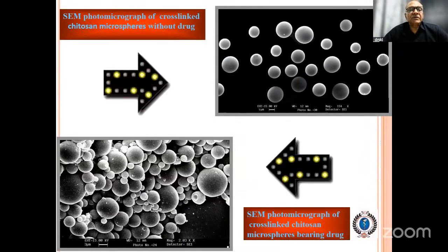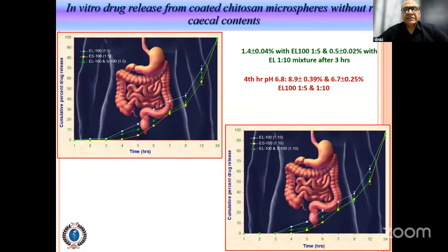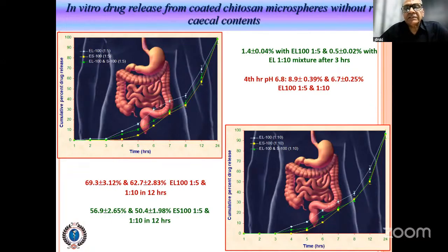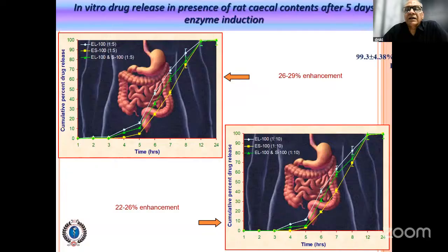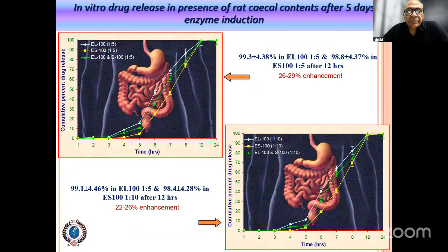This is a photograph of the cross-linked chitosan microspheres without drug, and this is the photograph of the chitosan microspheres bearing the drug. Different studies were performed to ascertain how much drug is released in the colon in the presence of the cecal content, when the delivery system reaches the colon. Chitosan is degraded by the polysaccharidase enzymes released in the colon, so most of the drug is released in the colon. Release studies were performed without the cecal content, with the cecal content, and with the cecal content after 5 days of enzyme induction.